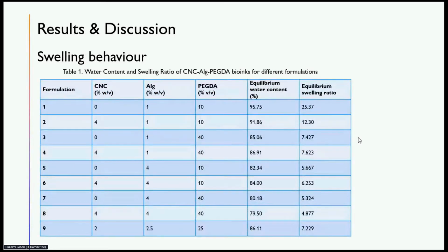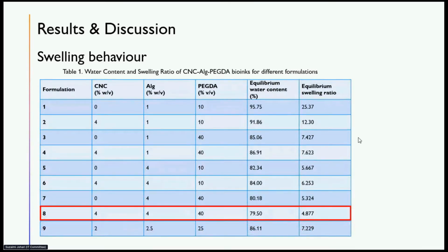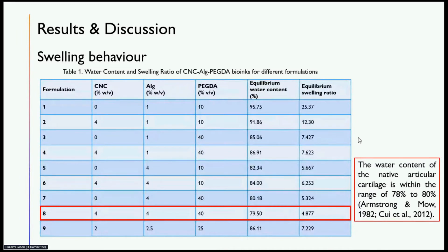Here from the data is the swelling behavior. We see that as alginate and PEGDA increase, the equilibrium water content and swelling ratio reduce. This is because of the increased cross-linking reaction that makes the uptake of water reduce. For formulation 8, we have a water content of 79.5%, which is actually within the range of the articular cartilage. This is good because we want the scaffold to resemble as closely as possible the actual tissue environment, so that regeneration is better and the cells can form their own extracellular matrix more easily.